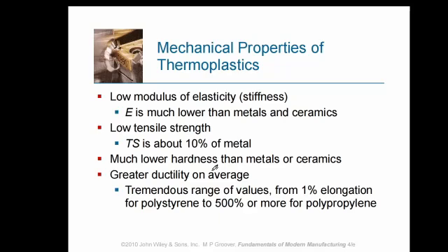That's ductility. You can stretch them to thinness, and they can be stretched from 1% to 500%, 1% for polystyrene to as high as 500% for polypropylene.